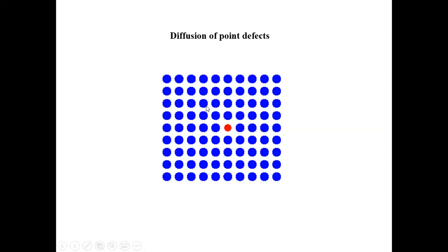So you can see that this particle can move around in the system. Again, this is highly schematic, but at least you see that it can hop from one possible location to another possible location, doing this random hopping, right? And also an interesting fact is that although it's schematic, as it does this random hopping, it has to squeeze through between a pair of densely packed blue particles, right? So this means that typically when you do the hopping, you will need some activation energy.